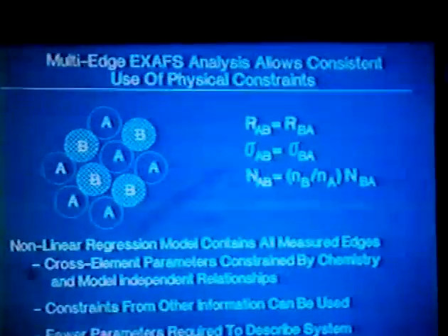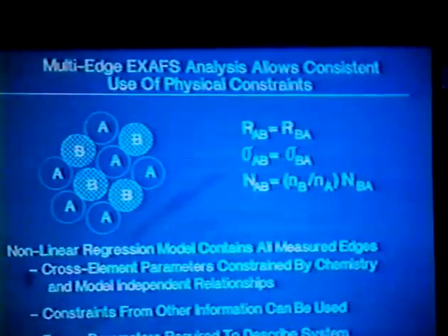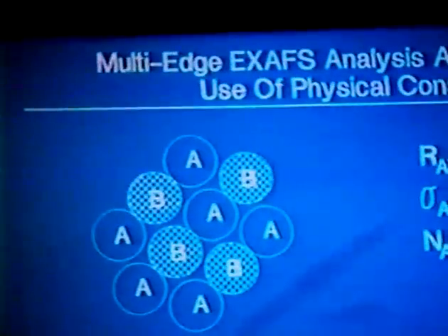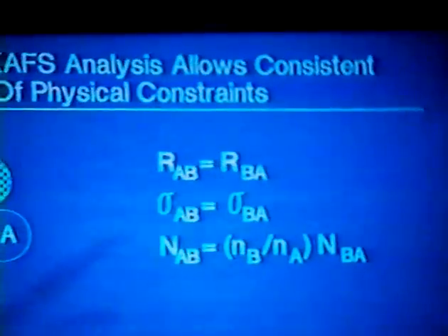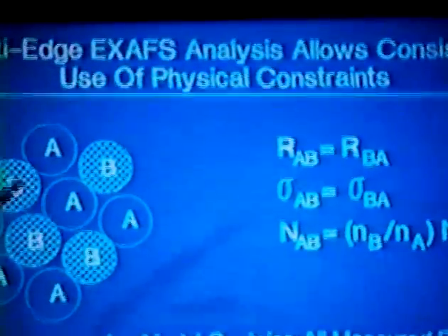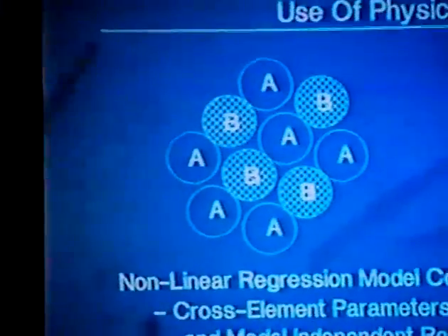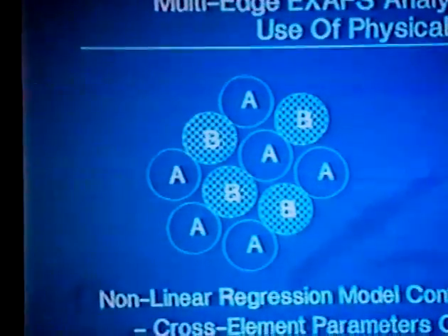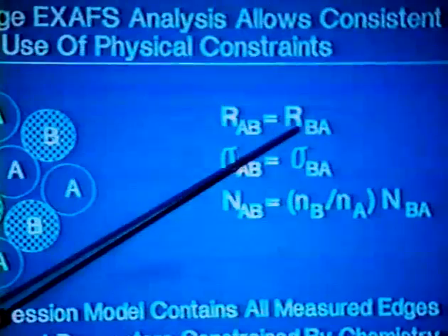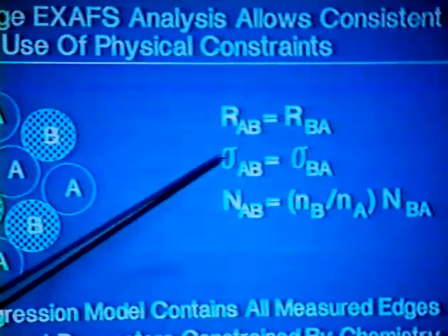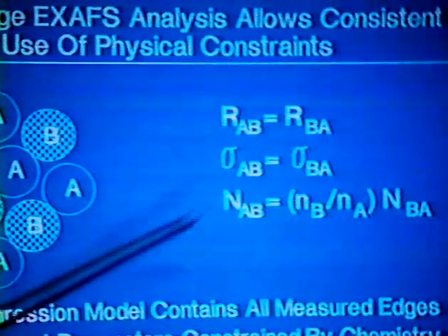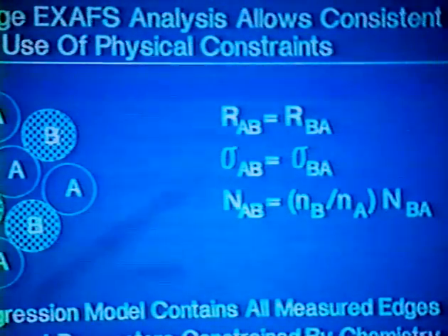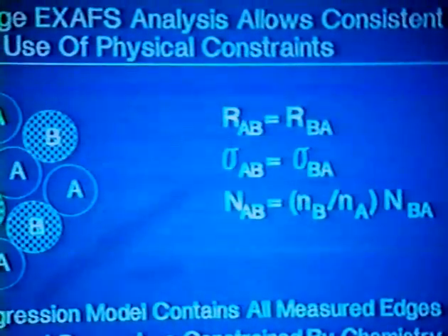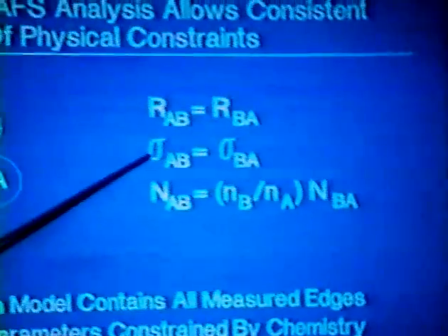Okay, one of the reasons, at least, that we like to work with systems that contain two interacting elements, not entirely scientifically guided. There's a practical reason, which has to do with how much information you can get. When you have spectra on two different types of elements which are interacting in the same sample, you can use a certain kind of information to interpret the two different spectra. For example, from the spectrum of A, I can get an AB distance. And from the spectrum of B, I can get an AB distance, and obviously those distances are the same. So when I analyze the spectra, I can force those quantities to be the same, and I'm effectively introducing new information to get a more reliable result.